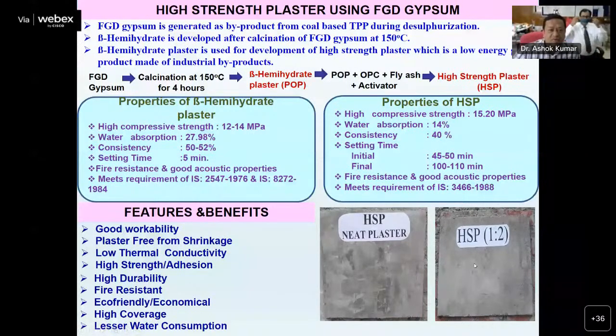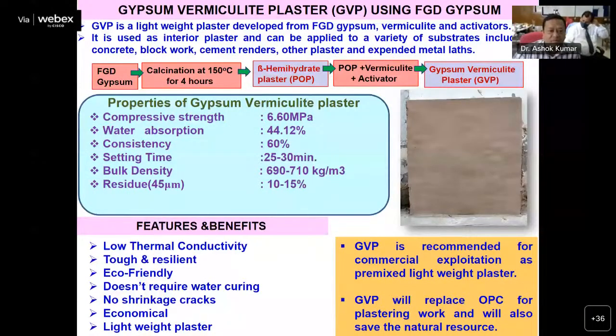The next plaster which we have developed from FGD gypsum is gypsum vermiculite plaster. This vermiculite plaster is a lightweight plaster which can be used for interior purposes. This has low compressive strength, and consistency is about 60%. It also has features like low thermal conductivity, eco-friendly, does not require water for curing, and low shrinkage. So this technology is also ready for transfer.